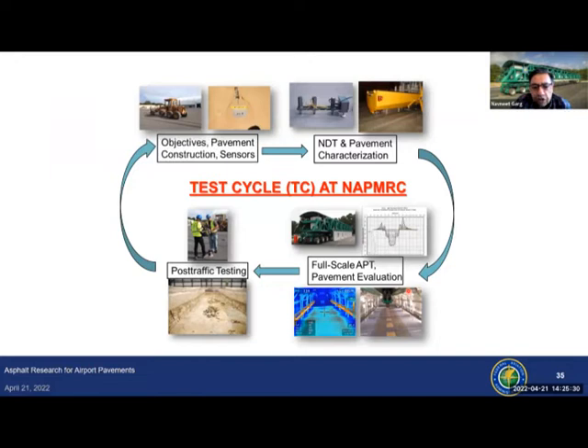And here is a flowchart for a typical test cycle at NAPMRC. The first step is to come up with research objectives. Based on that, we design our pavement cross-sections, construct those pavements, install sensors accordingly. And once we complete the construction, then we do non-destructive testing to characterize what we built and what kind of variability exists in the pavement structure. And after that, we do some response tests at different load levels, and then our traffic tests till complete structural failure. And then we look at the failure mechanism by cutting trenches.